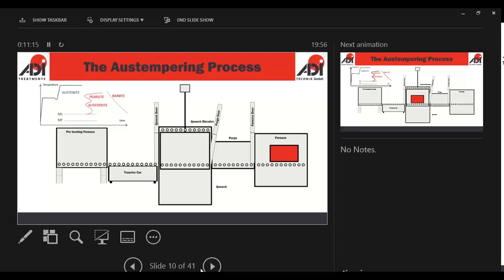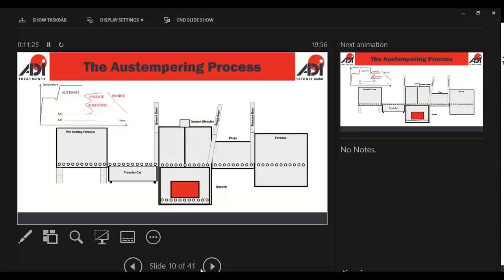The soak time is dependent on how heavy the casting is, the section thickness of the casting. Once it's had its soak, the parts transfer over and are lowered into the quench. That transfer time is consistent, it's 1 minute. It soaks in that quench, and the time depends on the temperature of the quench more than actually how thick the section is, because what we're trying to do is cool the whole casting down to the temperature of, say, 360 degrees centigrade before we start the transformation.